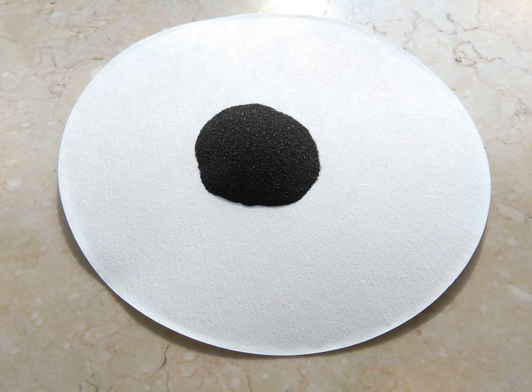Even though Potter reported the heat of combustion of SiO to be 200 to 800 calories higher than that of an equilibrium mixture of Si and silicon oxide, which could, arguably, be used as evidence that SiO is a unique chemical compound, some studies characterized commercially available solid silicon monoxide materials as an inhomogeneous mixture of amorphous silicon oxide and amorphous Si with some chemical bonding at the interface of the Si and silicon oxide phases. Recent spectroscopic studies in correlation with Potter's report suggest that commercially available solid silicon monoxide materials cannot be considered as an inhomogeneous mixture of amorphous silicon oxide and amorphous Si.